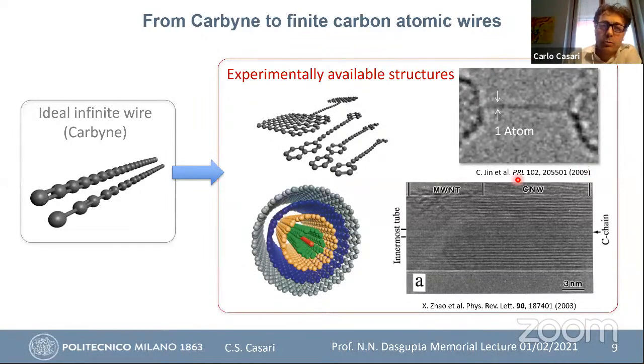And another way to have this kind of system, very easy to observe by electron microscopy, is this: the first work in 2003 showing the possibility to have a linear chain inside the core of a carbon nanotube. This is a multi-wall carbon nanotube. Here, if you count the number of lines, at a certain point you see that you have a single line in between here, the core, and this cannot represent a wall of the nanotube, but should be a carbon chain.